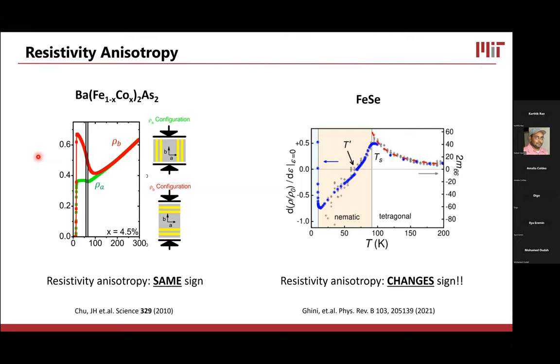So for most iron-based superconductors that I'm aware of, there's a negative sign. So the resistivity along the shorter B direction has a larger value than along A. For a few types of dopings, that can be flipped, and that's fine. But across temperature, it keeps the same sign. And that's true for a lot of different dopings in the pnictides.